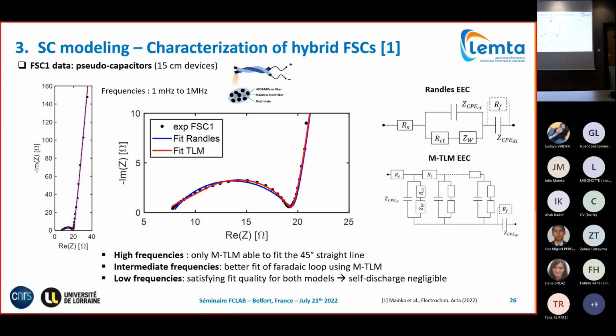Okay, I hope I understood it well. So you mean about 45 degrees? Yes, for my curve I'm getting less than 45 degree slope. That's what we observed as well, so that's a tricky point we're working on. In the literature you find two possible explanations. One is if you have inductive contributions, inductance.